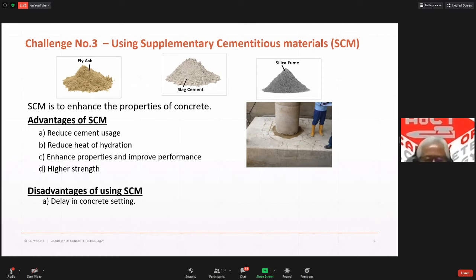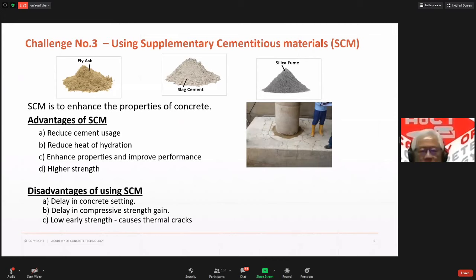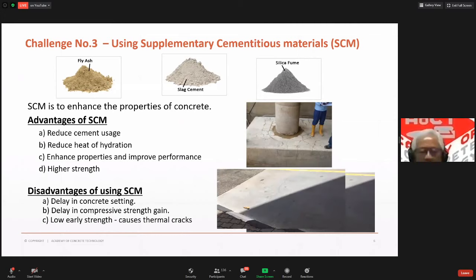Delay setting. The second thing is, of course, the compressive strength gain. You always test your concrete at 28 day strength. But because of, let's say, fly ash being added in, that's where you test your concrete at 56 days, right? And at the end of the 56 days, you always get a higher strength than the 28 days with the OPC. All right. So the third thing is very important. It actually